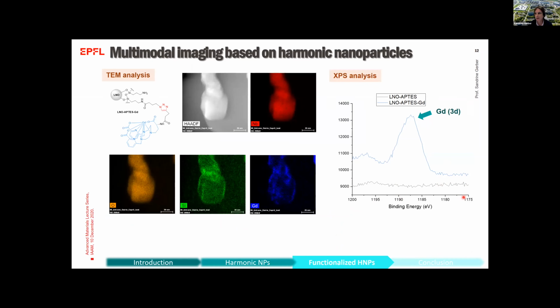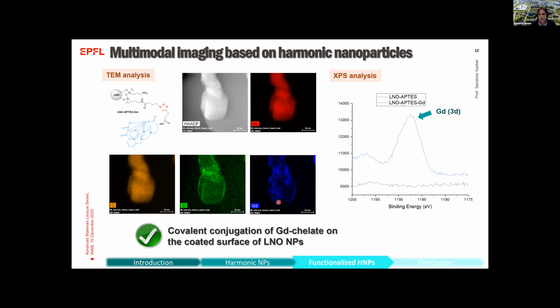Then in elemental analysis, it's also very clear that you have the elements that correspond to the composition of the material, for example niobium and oxygen. Then you have the silica layer around the nanoparticles, and finally here you can see the gadolinium distribution at the surface of the nanoparticles.